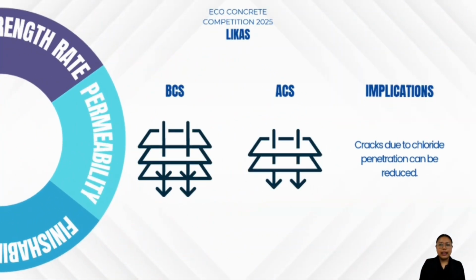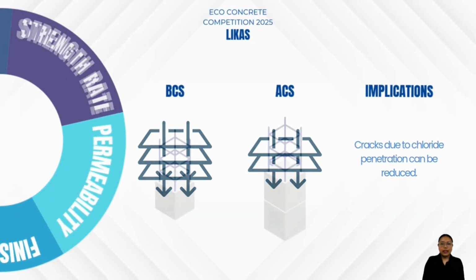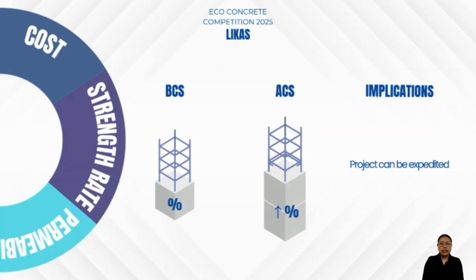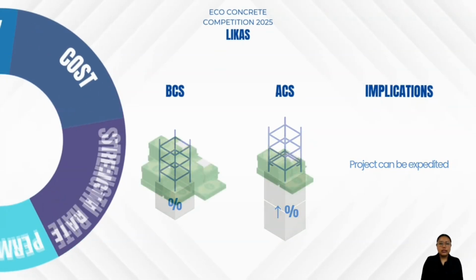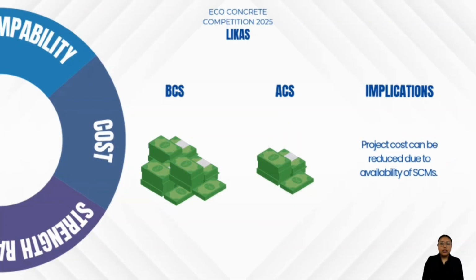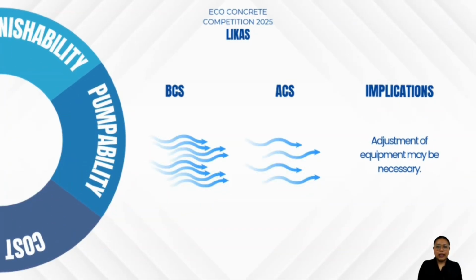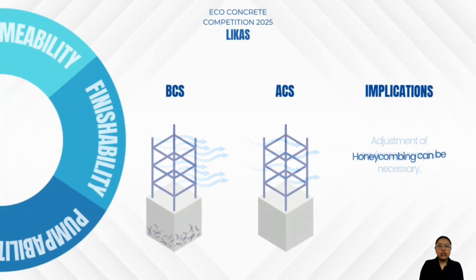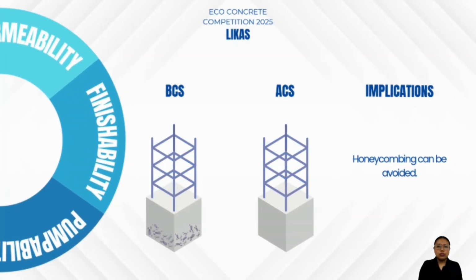Permeability is reduced in the ACS mix, minimizing chloride intrusion and the risk of cracking. Strength gain rate increases due to the synergy of silica fume and fly ash, accelerating construction timelines. Cost is reduced by replacing cement with highly available SCMs like fly ash and silica fume, lowering overall project expenses. Pumpability is slightly compromised due to the increased viscosity from high fly ash content, but this can be managed with equipment adjustments. Finishability improves as high fly ash content reduces heat-induced cracking, resulting in better surface quality.